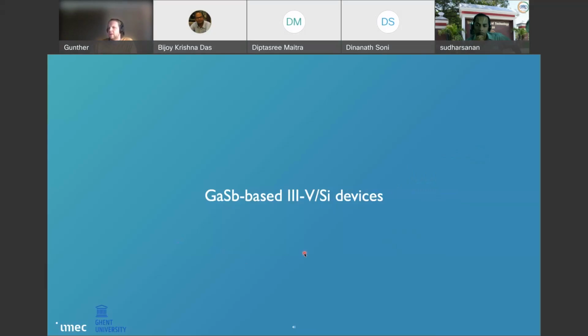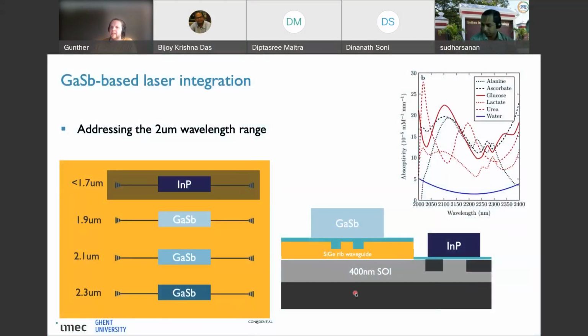And then finally, we are also looking at gallium antimony devices. This is still lowest TRL at the moment. But what is the idea? The idea is that using gallium antimony based materials, you can also address the 2 micrometer wavelength range. And the 2 micrometer wavelength range is interesting for spectroscopic sensing applications. Many biomolecules, for example, have characteristic absorption features in the 2 micrometer wavelength range. So for this, we also want to be able to transfer print gallium antimony SOAs onto a silicon photonics platform. And in principle, we can also combine it with indium phosphide and perhaps even gallium arsenide SOAs on the same chip. So this is work under development.